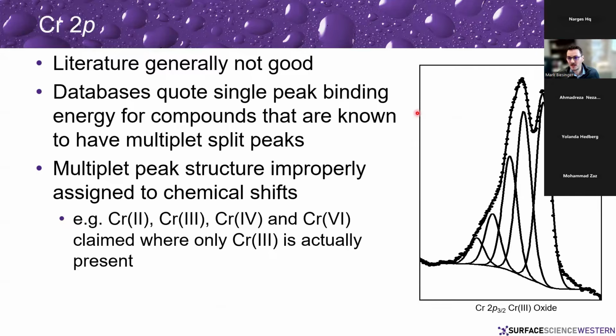If we get into species that have a lot of multiplet splitting. So when we first got into this, one of the first ones we looked at was the chromium system. The literature was generally not great. There was a lot of confusion out there. And again, I talked about how the databases were quoting a single peak binding energy, but for compounds that were known to have multiple split peaks. And a lot of people were assigning this structure to a whole bunch of chemical states when really only chromium 3 was present.